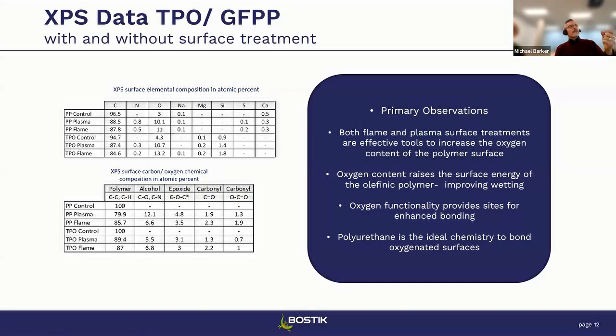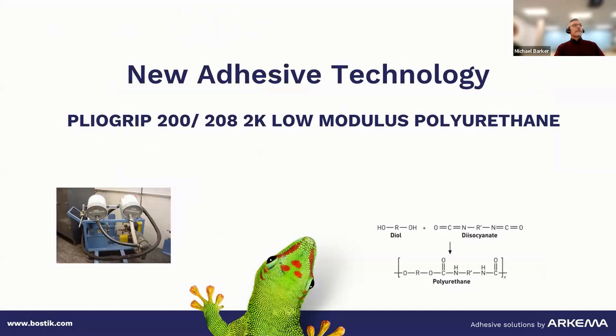And that varies from an alcohol to an epoxide, carbonyl, and carboxyl. So the takeaway from this is you can use either the flame or the plasma to introduce the oxygen into the surface of the polyolefin. That creates a higher energy surface, which then allows the polyurethane adhesive to wet it out.